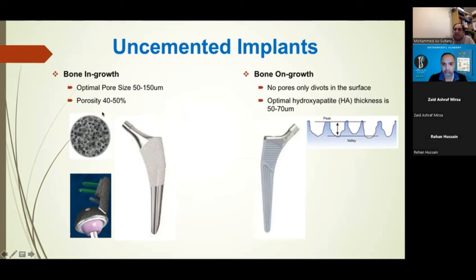And there are certain characteristics: porosity has to be about 40 to 50%, and the pore sizes have to be within a certain range to be sufficient, allowing bone to ingrow and incorporate into the surface, because that way it all acts as one and you get primary stability. You won't get any micromotion, because if you do get micromotion, you unfortunately never develop stability. You never get bone. With too much motion, you'll end up with fibrous tissue, and then you can get into Perren strain theory and all that kind of stuff, which is beyond the scope of this talk.